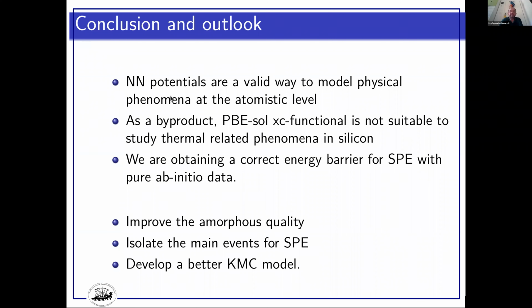But as far as neural networks are concerned, and I will finish with that, this looks like a promising way to model physical phenomena at the atomistic level. In the particular case of this solid phase epitaxy, we obtain the correct order of magnitude for the barrier energies, but it's important to have a good underlying DFT description. So at the end of the day, we will go back and check if the DFT that we are using is good enough for the property that we want to study.